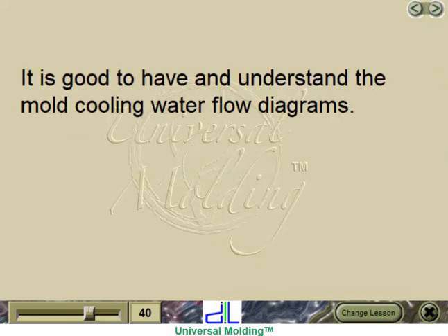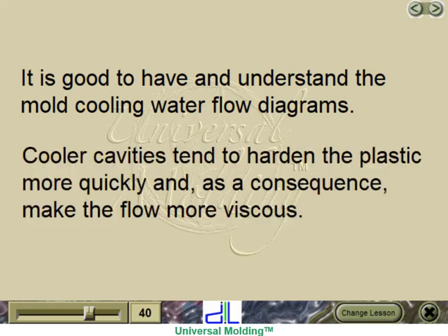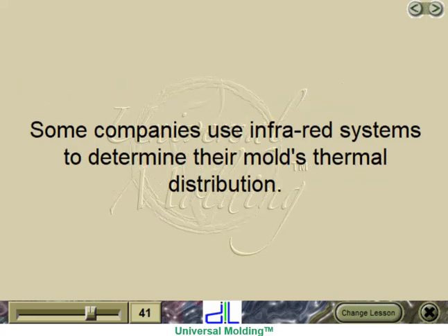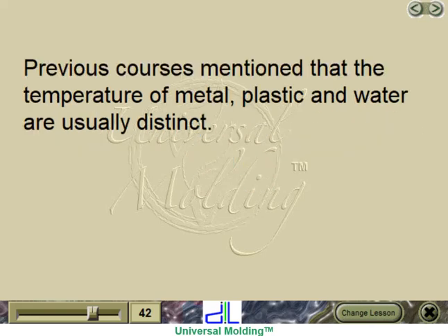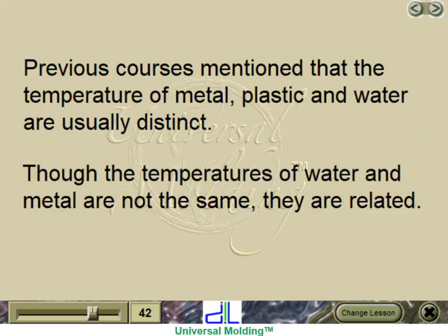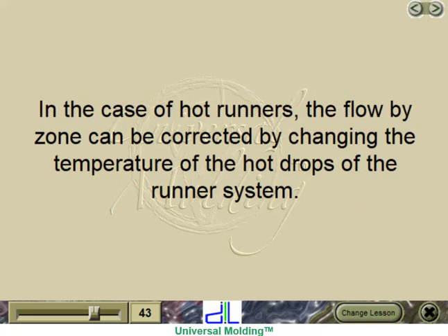Thermal unbalance. It is good to have and understand the mold cooling water flow diagrams. Cooler cavities tend to harden the plastic more quickly and, as a consequence, make the flow more viscous. Some companies use infrared systems to determine their mold's thermal distribution. The temperatures of water and metal are not the same, though they are related.